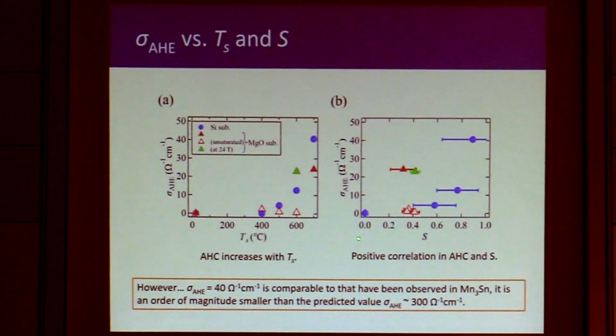We also see a positive correlation between the anomalous Hall conductivity and the chemical order parameter. One thing is that 40 inverse ohm centimeter is comparable to that observed in manganese 3 tin, but it is an order of magnitude smaller than the predicted value, which we don't know why.